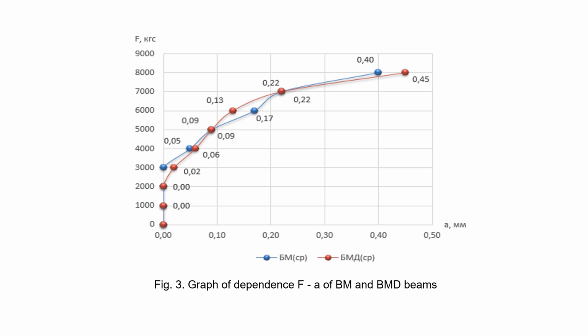The first normal cracks appeared in the pure bending zone at a load of 0.3 to 0.4 of the destructive load. Further increase of the load led to the appearance of new normal cracks. For the BM and BMD beam series, the width of the crack opening at 5.0 T and 7.0 T is the same, and in other cases the difference ranges from -20.0% to 23.5%.